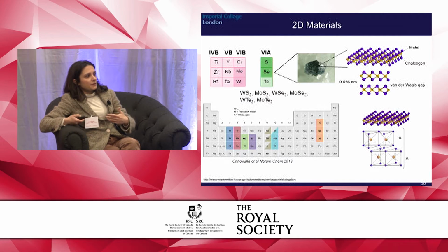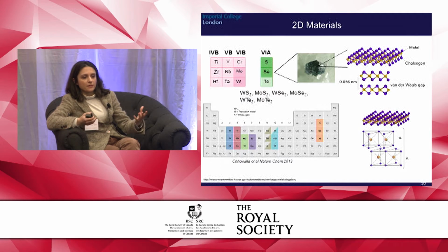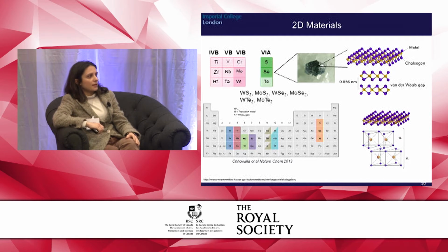As I mentioned, along with graphene, now we have a wide range of other 2D materials that are currently explored, in particular for their optoelectronic properties. And amongst these several other layered compounds, we can think of isolating single, individual layers from those compounds. There is this large family of metal dichalcogenides, so compounds of molybdenum and tungsten with sulfur and selenium. And their atomic structure is formed by a sandwich structure between one metal atom and two chalcogen atoms. This is an individual layer.